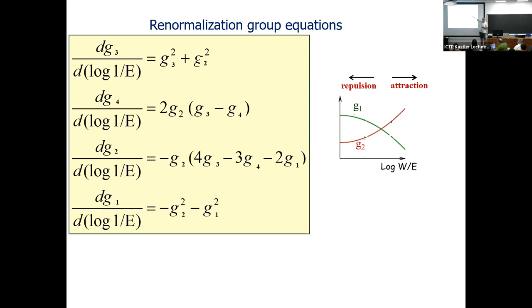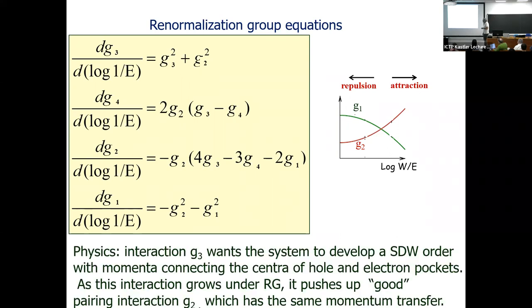You get a scale. It's interesting: the system by itself develops a scale below which it has attraction. So it develops, if you like, an upper cutoff for any attractive interaction. And there is a reason why this happens, because there is an interaction in the particle-hole channel which wants the system to become antiferromagnetic.